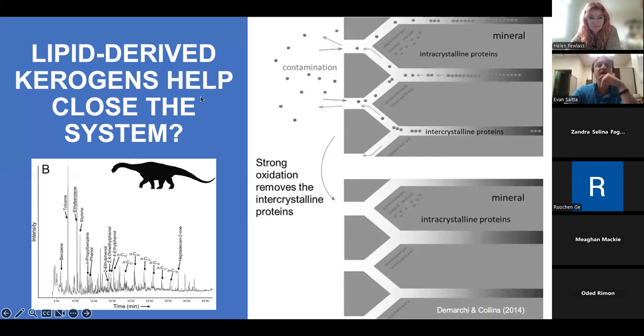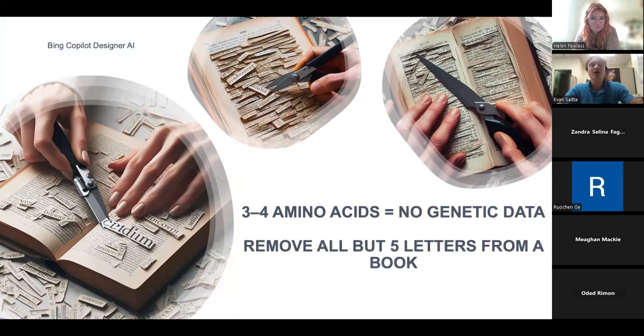Another aspect that's really interesting is this kerogen result, these organic geopolymers that we're finding. They could, for example, derive from the original lipids. So these are like Maillard-type reactions, or similar to Maillard-like reactions, I should say. Cross-linking, polymerization, and perhaps the formation of these geopolymers help to close the system within the calcite. And so they might actually be playing a role in the preservation and trapping of these amino acids.